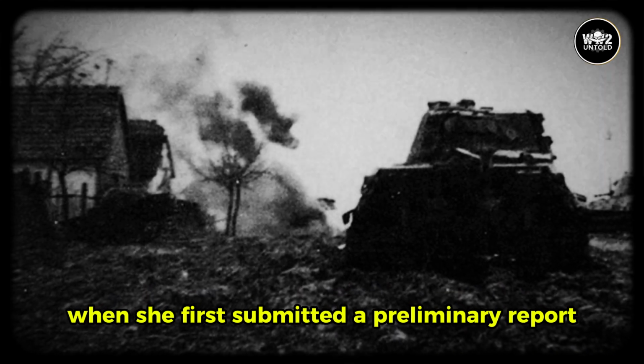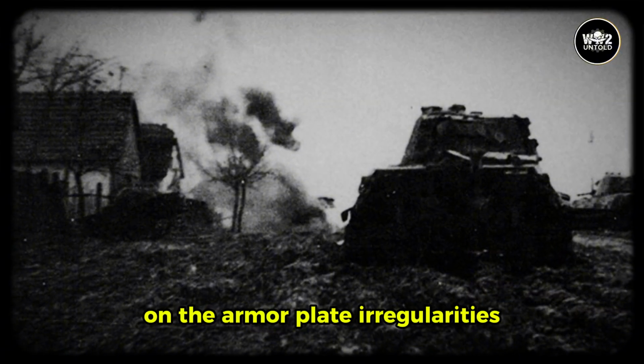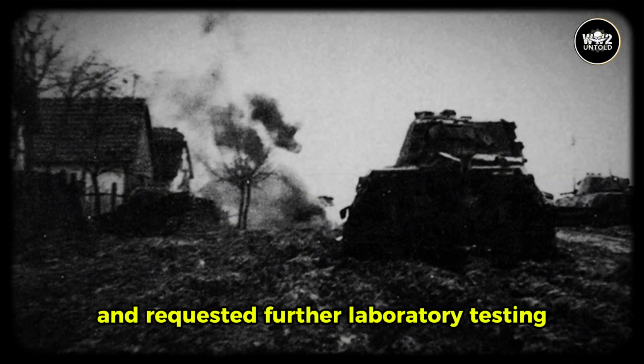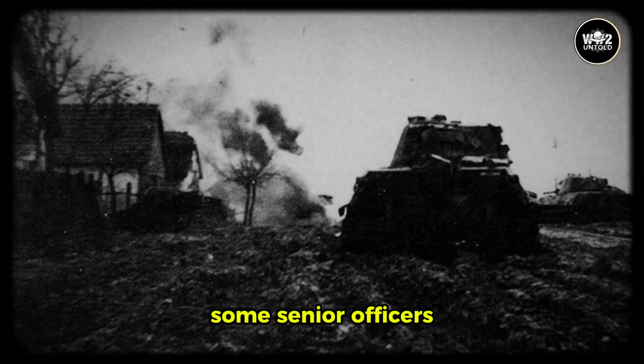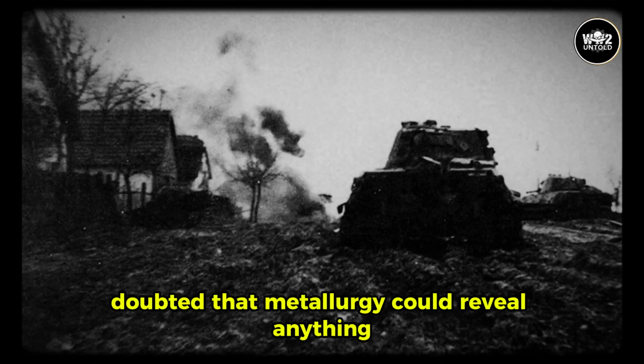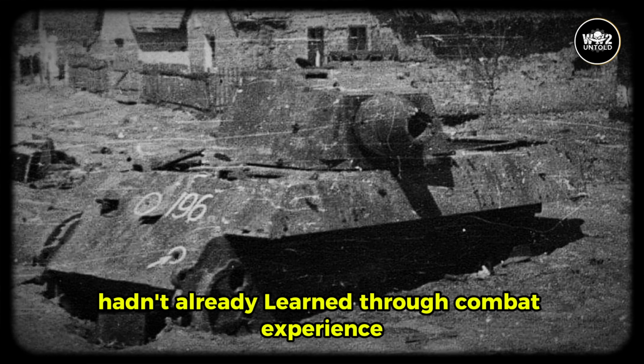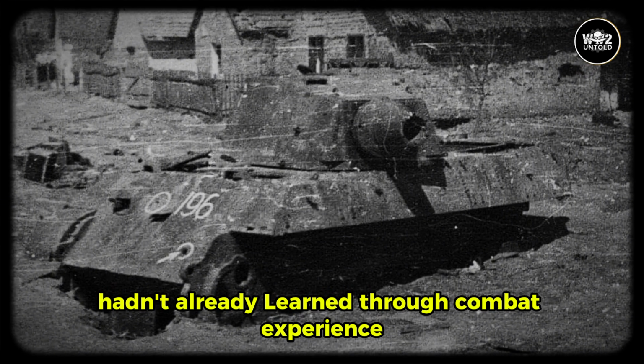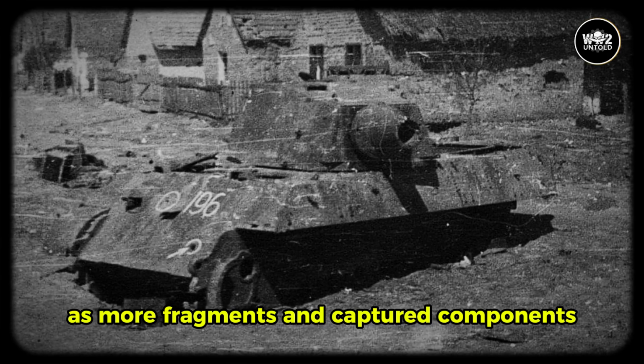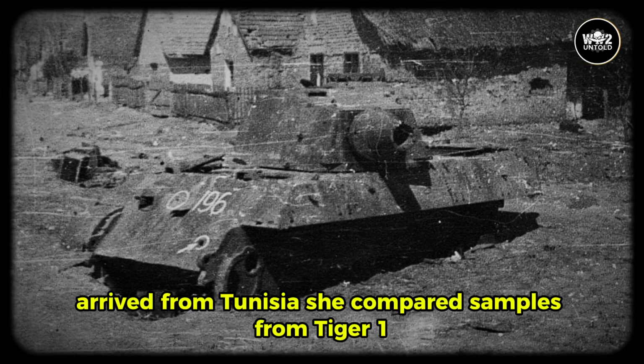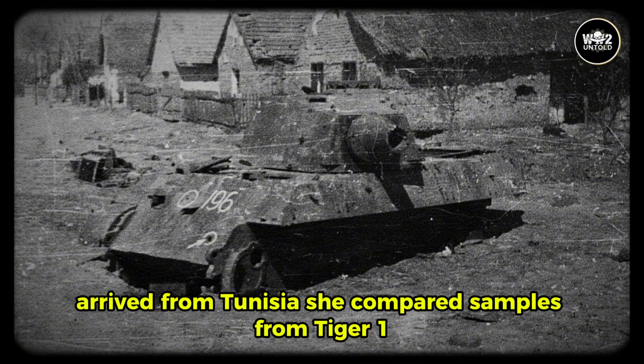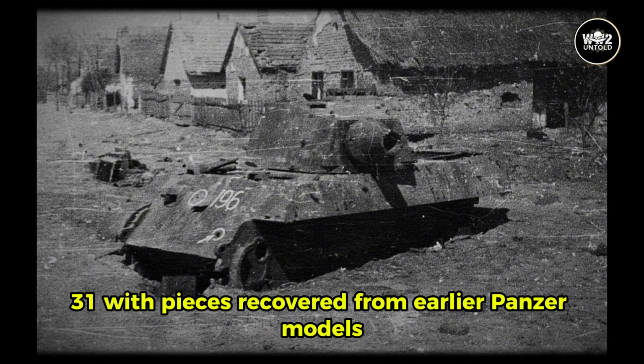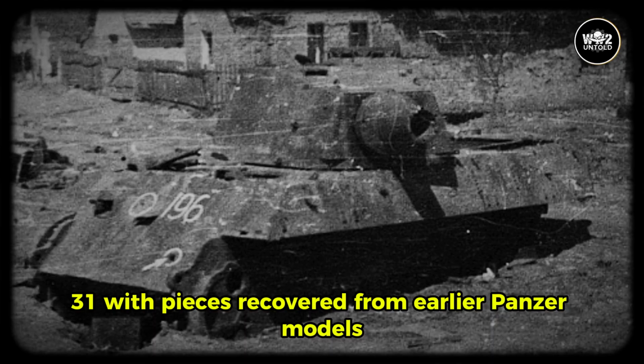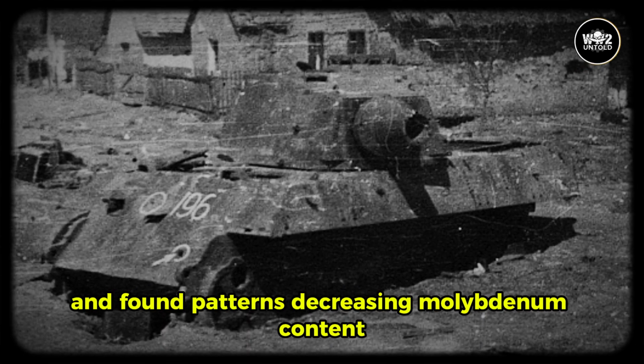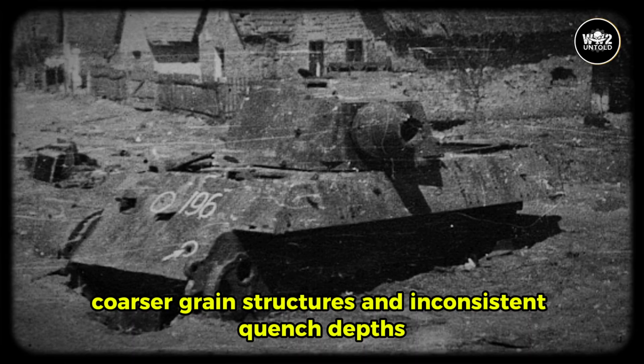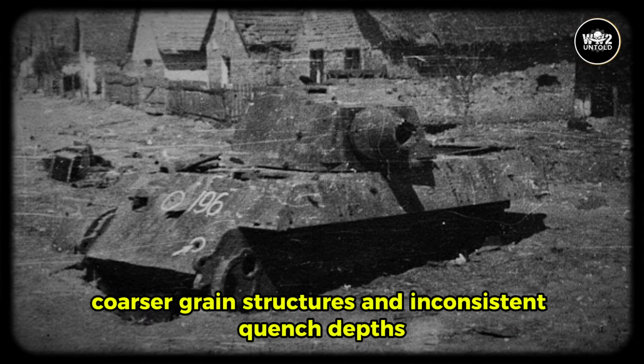When she first submitted a preliminary report on the armor plate irregularities and requested further laboratory testing, some senior officers doubted that metallurgy could reveal anything battlefield commanders hadn't already learned through combat experience. But those doubts faded as more fragments and captured components arrived from Tunisia. She compared samples from Tiger 131 with pieces recovered from earlier Panzer models and found patterns: decreasing molybdenum content, coarser grain structures, and inconsistent quench depths.